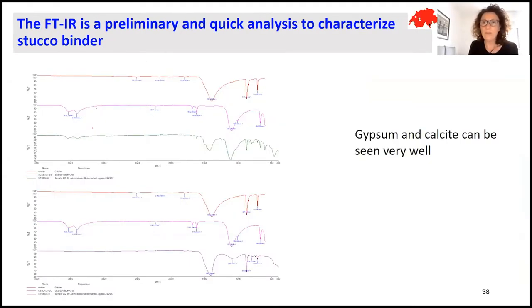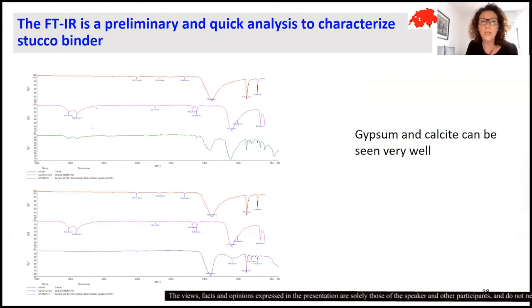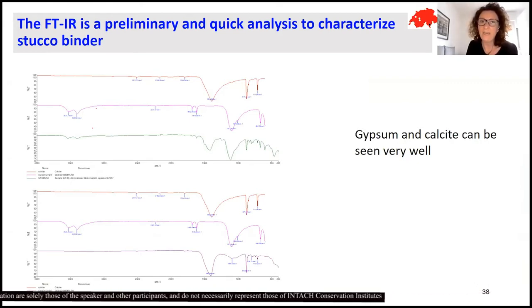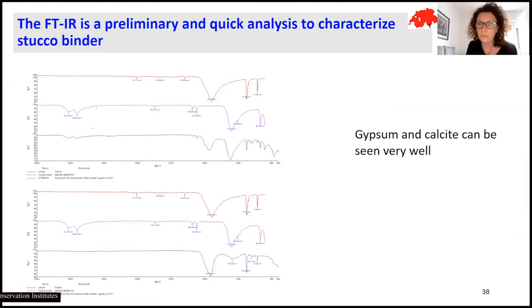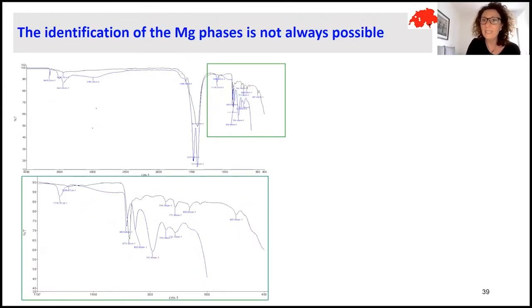In order to characterize the recipe and to understand if there is gypsum in a mortar, it's possible with observation under the microscope, but if the quantity of gypsum is not that much, or if we don't find any gypsum residues, which is sometimes possible, we can use another technique such as FTIR, infrared spectroscopy, with which I can very easily get information about the presence of gypsum and lime, because both calcite and gypsum are very easily distinguishable. On the other hand, with this technique, it's not always possible to identify the magnesium component very well because of the overlap of the two signals of calcite and magnesium carbonate.